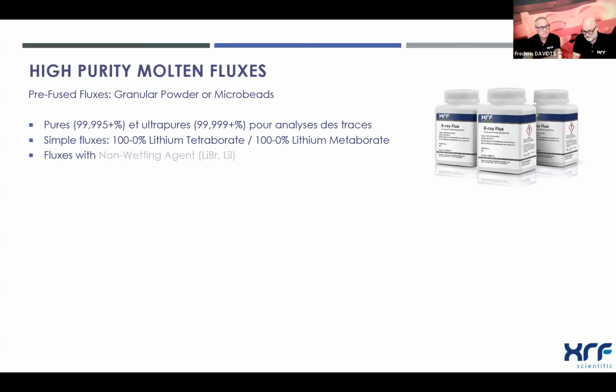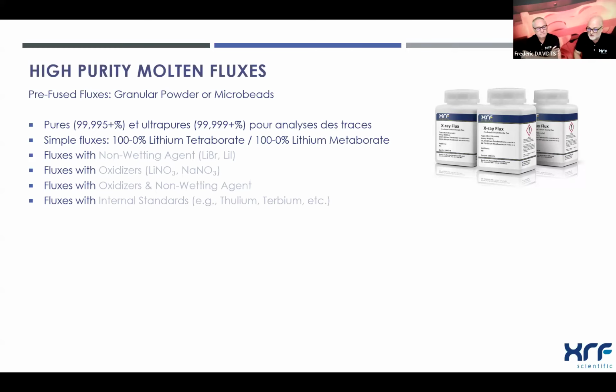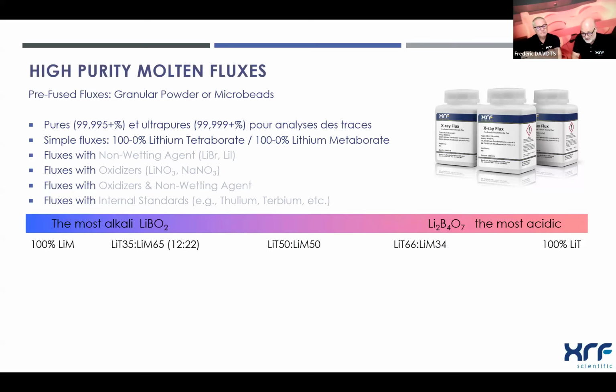The flux are often made of 100% lithium tetraborate up to 100% lithium metaborate and a mix of both. And you can have the additives. So you can have a flux with a non-wetting agent, lithium bromide, lithium iodide, or you can have it with oxidizer, or you can even have it with oxidizer and non-wetting agent. So it's very useful because you don't need to weigh separately the different chemicals. And also you have flux with the internal standard, like you spoke about. And for example, the thulium is really often used in the nickel mining world, especially for analyzing the nickel, because you have very good results for that.